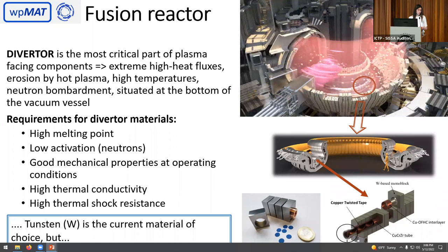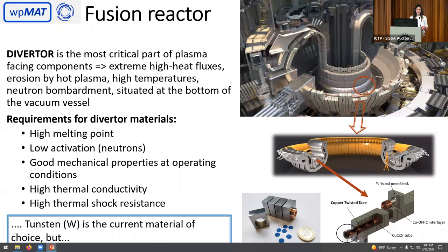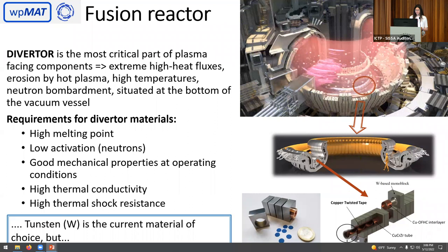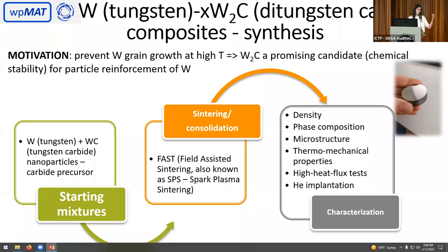We need to choose a material with a very high melting point. Tungsten is a natural choice because it's the metal with the highest melting point, and this has been proven in scientific research and development efforts. But it also comes with some drawbacks. Tungsten recrystallizes when it reaches 1000 degrees Celsius. One solution is particle reinforcement by including oxide and carbide particles into the tungsten matrix. Another way is to include tungsten composites with tungsten carbide.